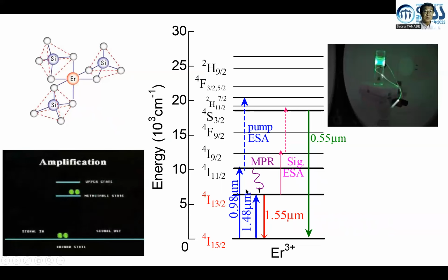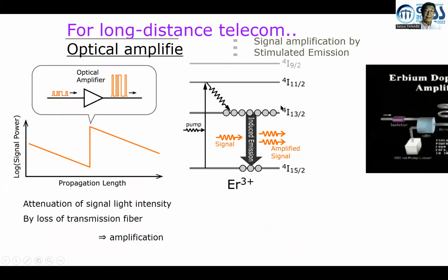which quickly relaxes into the first excited state by multi-phonon relaxation, because of the small energy gap. Because of the very stable excited state, the 4I13/2 level, very high quantum efficiency emission is observed, as well as green up-conversion, which is a result of two-step excitation into an upper state. But this works, and actually this is the propagation length of optical telecommunication.